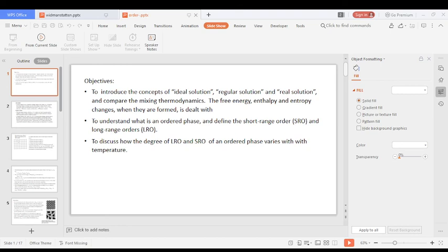So what is the impact? Why should we be worried so much about the ordering? When ordering takes place, the mechanical and physical properties change. The symmetry of the crystalline phase will decrease when it moves from a disordered to an ordered state. In an ordered superlattice, dislocation slip is difficult because of the restricted number of slip systems or the presence of antiphase boundaries. Antiphase boundaries block the motion of dislocations. Physical properties like electrical and magnetic properties also exhibit different behavior.